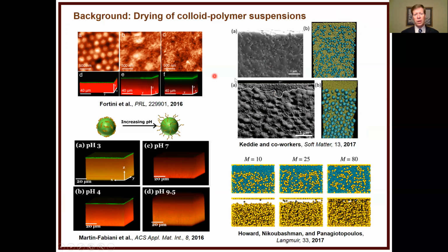And one of the ways to do this is to perform simulations where there have been great simulations, for instance, in the Keddie group and others like the Panagiotopoulos group at Princeton, where they've looked at binary systems and particle-polymer systems to understand the size ratio and how that caused partitioning in these systems. And so we all know that's driven by a Peclet number. For most of the things we're going to talk about today, the Peclet number is high because the viscosity is relatively high and the diffusivity is relatively low. And so I'm not going to get too worked up about that because we also are going to have particles